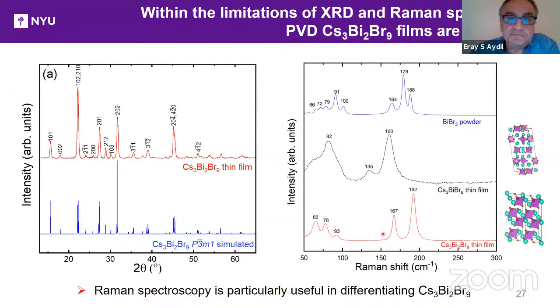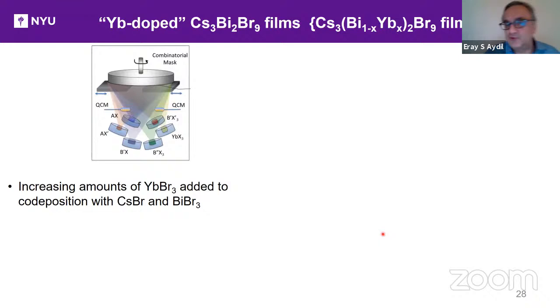So I want to get back to the quantum cutting. I started introducing this material and I said, well, could this be a quantum cutting material? Is it a candidate? So we took this material and we doped it with ytterbium, making films, if you will, assuming that ytterbium goes into the bismuth position, basically alloys or solid solutions of bismuth and ytterbium. So we added increasing amounts of ytterbium bromide to co-deposition with cesium bromide and bismuth bromide.